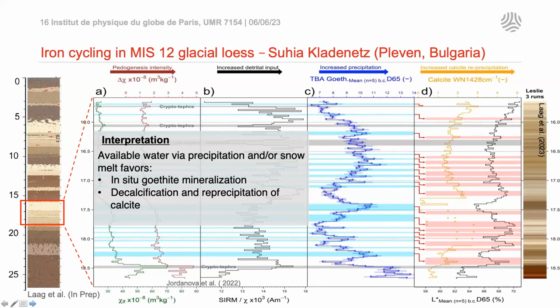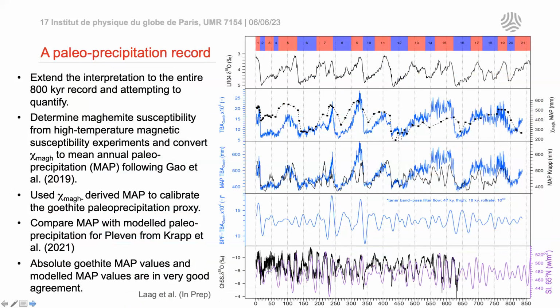So if we take this information and try to extend it across the entire record and attempt to quantify, the goethite derived data is the second plot from the top, in blue. What Christian then did, which are the black dots on that same plot, is take susceptibility of maghemite determined from KT curves, converted to mean annual precipitation following the paper of Gao. So it's a transfer function that is not for this area, it's for the Chinese Loess Plateau.